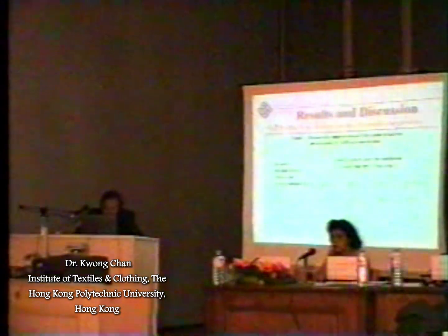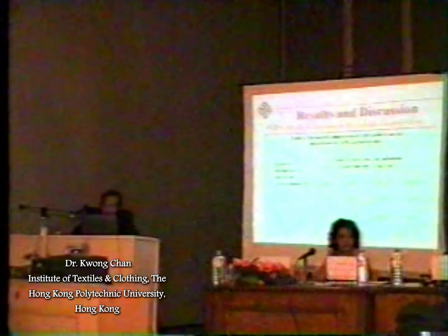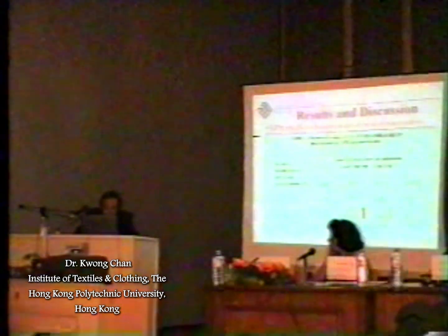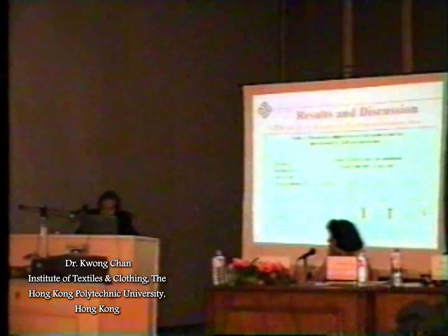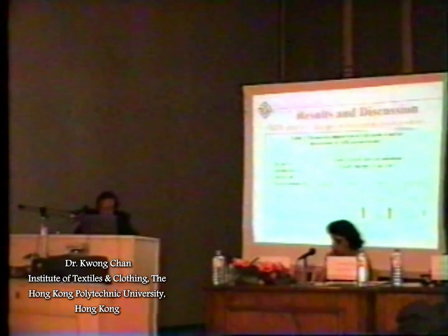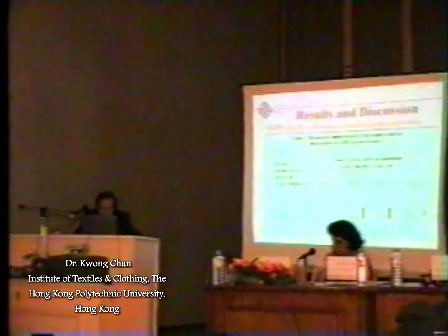The changes in chemical composition can be studied by XPS, and the table shows the XPS results. The results show that the oxygen to carbon ratio and also the nitrogen to carbon ratio increased significantly, but reversed to a lower level after irradiation of around 2,000 pulses.